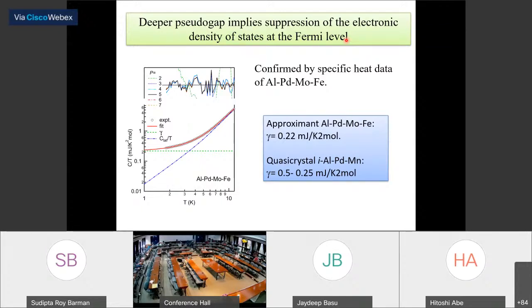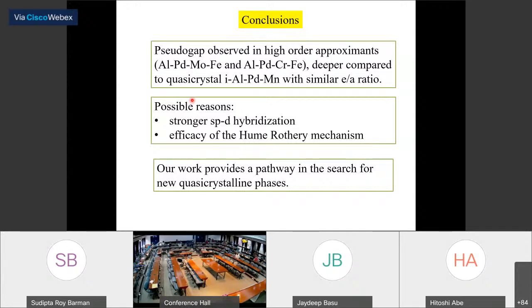There are possible reasons. We say there are possible reasons because the theory could not be done. The details of the structure are not even known for AlPdMn. What is the structure? All the theory is done on a model structure, and that too on the approximants. So from the experiment, we say that there are possibly two reasons: stronger SPD hybridization, or it is possible that the efficacy of the Hume-Rothery mechanism is better in the case of the approximants because of the translational periodicity. But nevertheless, our work provides a pathway in the search for new quasicrystalline phases, because if we find an approximant which has a deep pseudo gap, more or less we can expect a quasicrystal around that value in systems with similar composition. Thank you.